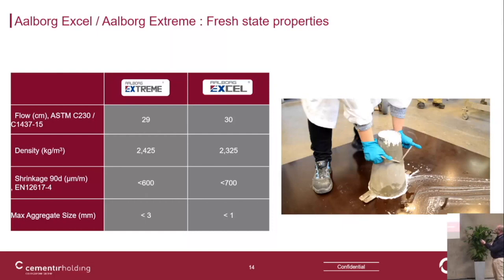In traditional UHPC, you are often at the level of 1,000 microns per meter, and here we have results of around 600 for the Extreme and 700 for the XL. And then, of course, the main difference is the maximum particle size. 3 millimeters for Aalborg Extreme, 1 millimeter for Aalborg XL.